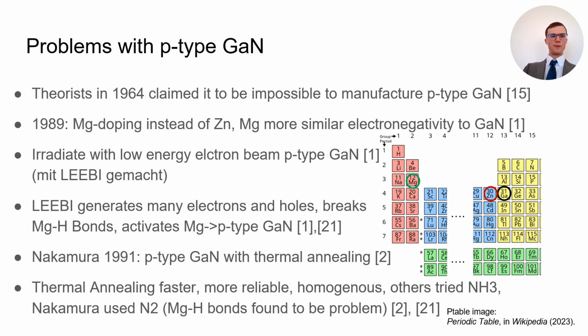However, Nakamura had an even more genius method, which was simply thermal annealing, which just means heating up to a very high temperature and then cooling very slowly. He also used nitrogen N2 and not NH3 ammonia, and with this the hydrogen was out of the picture and the Mg-H bonds were less of a problem.